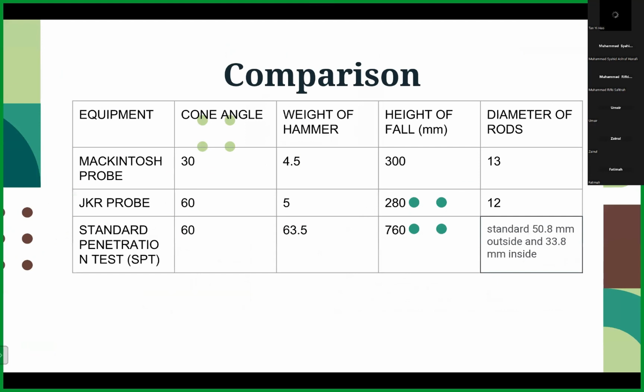So this comparison between Macintosh, JKR probe, and SPT. So SPT, this test is the most popular and economical means to obtain subsurface information. So as in the table, for Macintosh probe, the cone angle, as I mentioned before, is 30 degrees. For JKR probe and SPT is the same, which is 60 degrees. So for the weight of hammer, Macintosh 4.5 kilo, for JKR 5 kilo, and for SPT is 63.5.